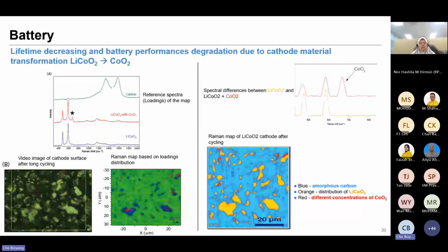This example is on the battery analysis. So this is for the cathode material. For lithium battery, the cathode material, lithium cobalt dioxide, if it starts to degrade, then it will give you this cobalt dioxide peak. So it starts to react and become another material. If we map the area of the cathode material, this red color region is those area with this small peak here. So the researcher will get the information like why the battery starts to degrade. Maybe because the cathode material starts to degrade, and you know where the degradation points of your cathode material are.